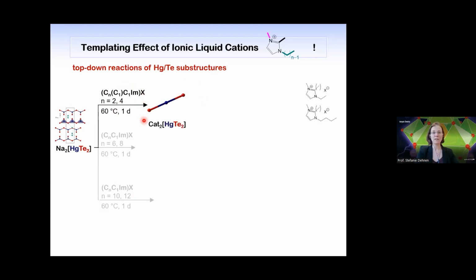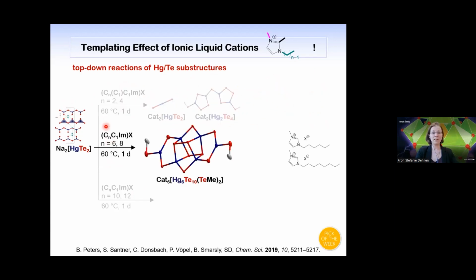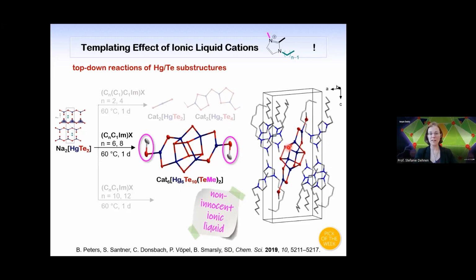And the results showed us that in the short alkyl chain ionic liquids, we get a monomeric unit. So we just split this zigzag chain, or we have a partial oxidation of neighboring tellurium atoms to form these five rings. And then we have a one-dimensional strand. Getting to the longer chain imidazolium cations, we find a kind of cluster molecule. And the special thing about this cluster is that we have a methylation on the terminal ligand, which was absolutely unexpected. So we have a non-innocent ionic liquid, and I'll get back to that in a moment. And the reason why we form exactly this cluster is because it fits perfectly into the counter-ion sphere of these longer alkyl chain imidazolium cations.